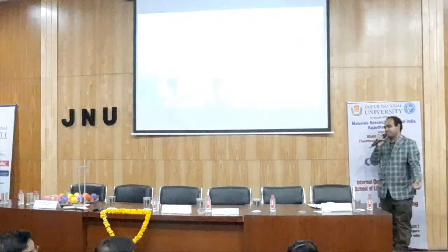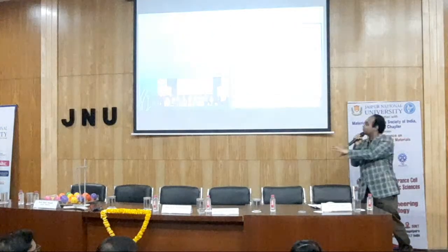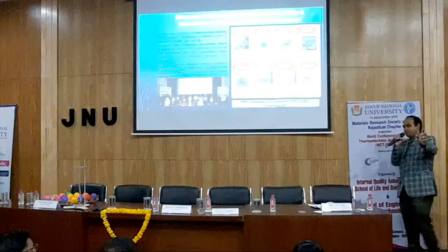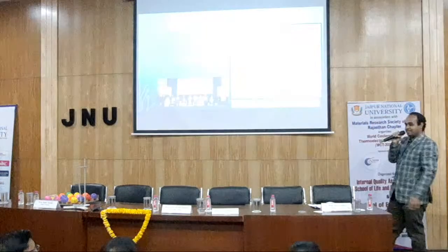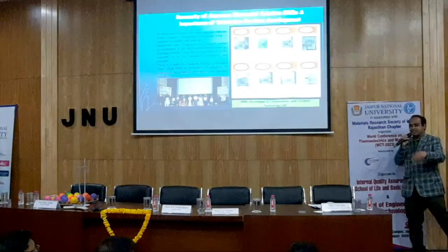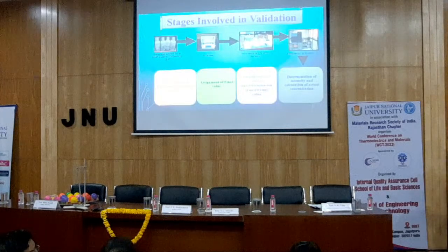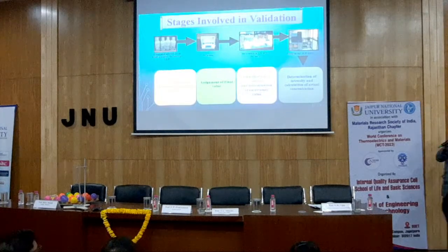For development of these BNDs, we need to get a source material. Source material purity is assessed, and it is traceable to SI unit by mass. The source material is then converted to a batch of production, and the complete batch is made of the BNDs. After that, we take some samples out of it and do the validation to cross-check whether the gravimetric value we obtained is in correlation with the instrumental technique. So we go for validation of these BNDs, and finally after certification, they are released in the form of BNDs.